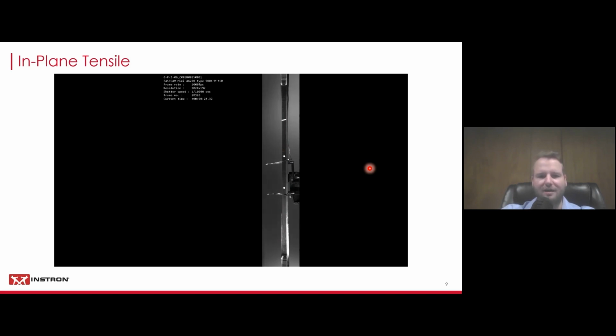Even with that high resolution, it's pretty much impossible to tell when the break actually happened. It just kind of explodes once that maximum strength is reached. And what you also can see very clearly in this video, there's also a lot of dust and really, really fine small particles. So you need to make sure that your equipment is protected from that, because carbon fiber is electrically conductive. So if that gets into your electronics, it will harm your test frame, but also, of course, make sure that your operators are protected from that harmful dust and debris.